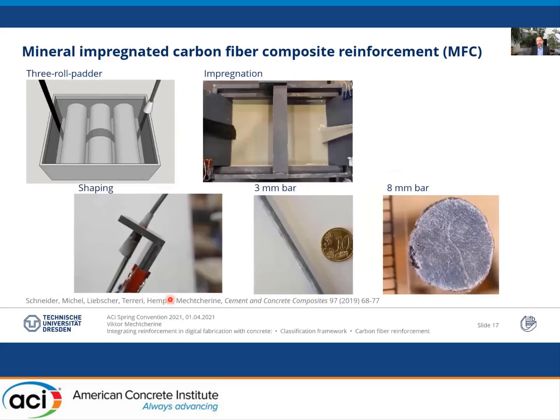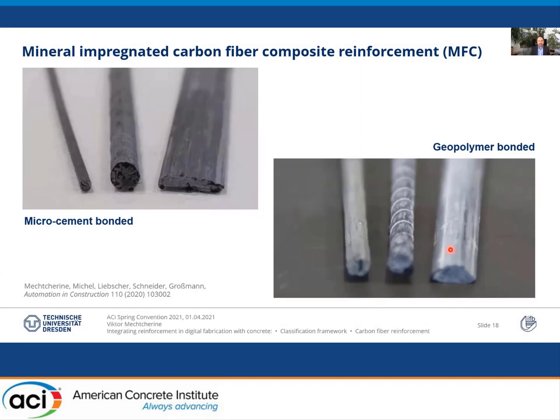We developed this technology a few years ago. The trick is using a very fine suspension — details are in the paper — with special impregnation technology enabling very homogeneous impregnation of the fiber. In a bar of 8 mm diameter, you have half a million individual carbon filaments, all of which must be separated with bond material between them, with no large bundles allowed. This requires very good distribution technology. We work with both cement-based suspension and geopolymer suspension.